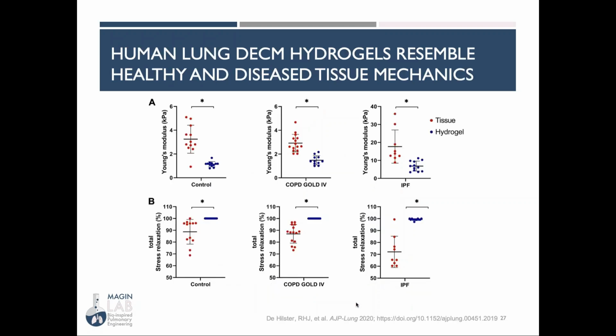If you take these materials that have been decellularized, lyophilize them, crush them up into a powder, and then turn them into hydrogel biomaterials, you can see that decellularized extracellular matrix, or DECM, hydrogels resemble healthy and diseased lung tissue mechanics. This is a study out of Jeanette Burgess's group, and they're showing Young's modulus here. In red is the tissue that they tested, and in blue is the hydrogel made out of the decellularized tissue.